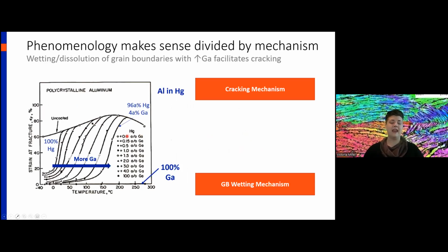You can also look at a plot like this, where this is polycrystalline aluminum, this is temperature, and this is the strain to failure. Each of these curves is a different amount of gallium in mercury. Over here is pure mercury. This curve is 4 atomic percent gallium in mercury. And if you'll note down here, this is the 100% gallium curve.